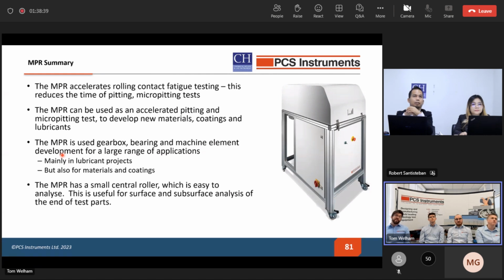The summary: the MPR is an accelerated rolling contact fatigue tester. It can reduce the time it takes for pitting and micropitting tests compared to other standard tests out there. It can be used for a wide variety of applications to develop new materials, looking at the coatings, the lubricants. It can mimic the parameters found in gearboxes and bearings, machine elements for a wide range of applications. And because of its free contact geometry, we can look at the real design lives for these applications in a very, very manageable short space of time.